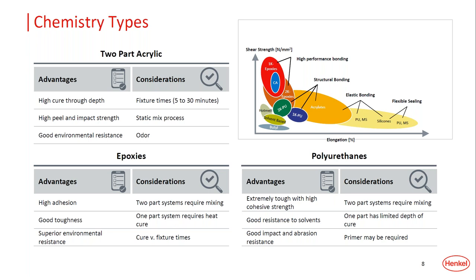Next, we have our one- and two-part epoxies. Epoxies are known for their excellent fluid resistance and toughness. One-part epoxies generally need a heat cure, while the two-part epoxies can be mixed and cured at room temperature. Epoxies are like two-part acrylics because they bond very well to plastic and metal substrates. This chemistry offers you high strength and a rigid bond. The trade-off here, though, is they don't have great elongation like some of the other chemistries do.